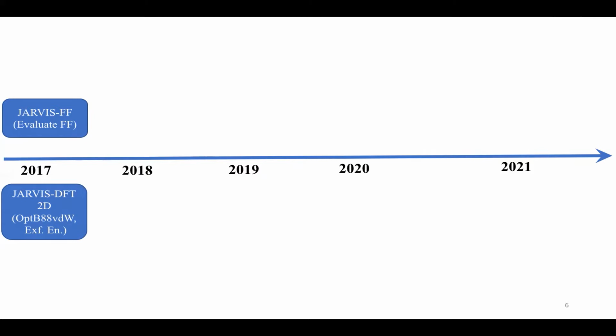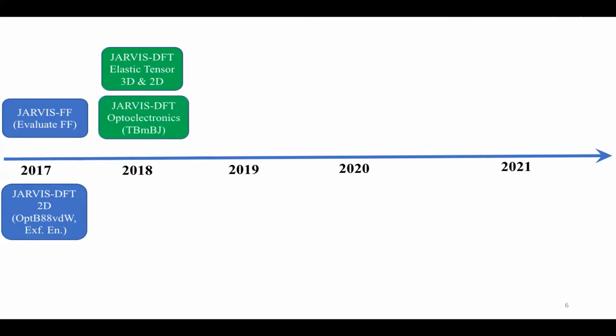So that was 2017. In 2018, using this OptB88vdW functional, we developed an elastic tensor database using the finite difference method for 3D and 2D systems. We also saw that there is a need for better band gaps in DFT. Standard DFT underestimates band gaps severely, so you want something that is closer to experiments and reality. Higher level methods are more time consuming, so we wanted to find a middle ground. The meta-GGA, something like the Tran-Blaha modified Becke-Johnson, was pretty useful, so we made a database for that.